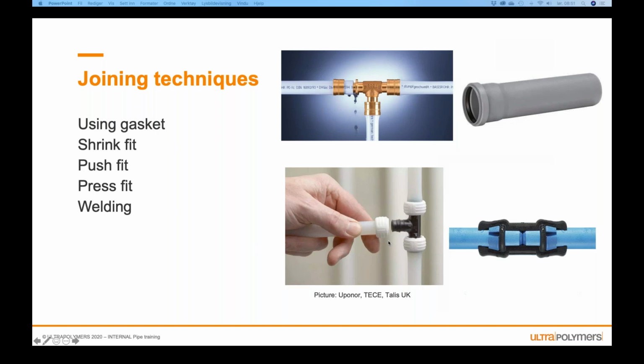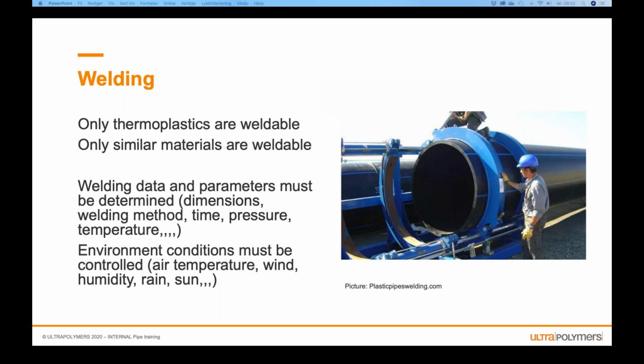And I will go a bit deeper into welding, because welding is also important to know about. If you're going into infrastructure, you need to have a welding department. So only thermoplastics are weldable, but they are also only weldable with similar materials. It is possible to weld a pipe onto polyethylene, but it's not possible to weld a polypropylene pipe onto a polyethylene rotomoulded product. And it's very strict when you are welding pipes. You need to control the dimension, method, time, pressure, temperature, and that has to be logged. And if the municipality wants to know about this, the log, you are obliged to give it to them.